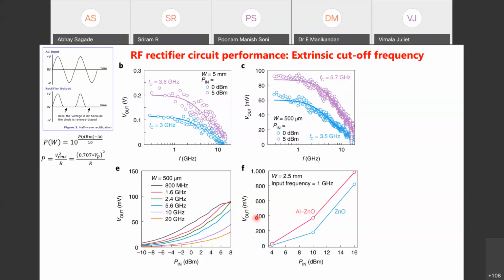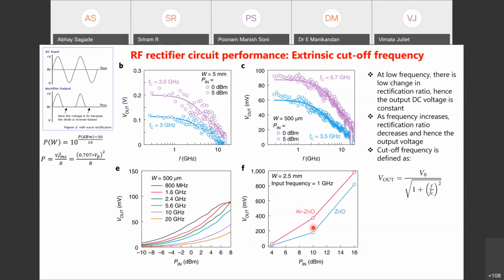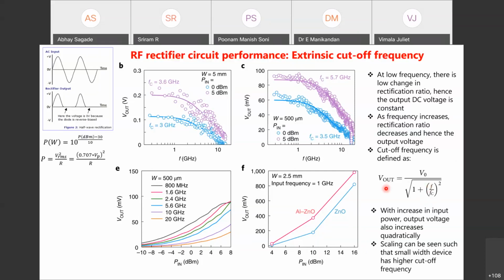And that's why we have plotted in this graph the maximum output voltage obtained as a function of input power. So this is the formula you can use to obtain your cutoff frequency. These data points are experimental data, and the line is a line fit obtained from this equation. So what you can see is that the smaller the device, the better its performance, called scaling, at higher cutoff frequency.